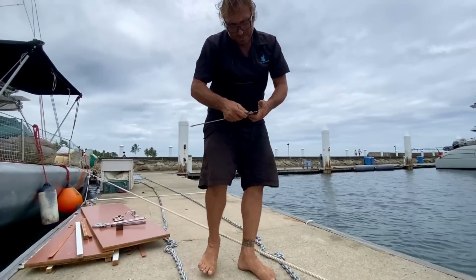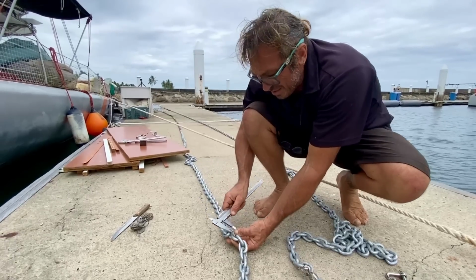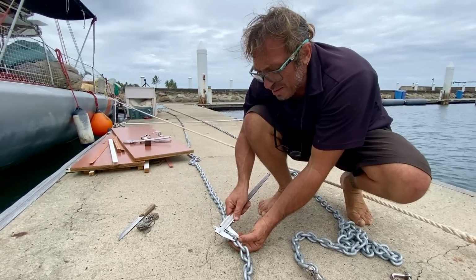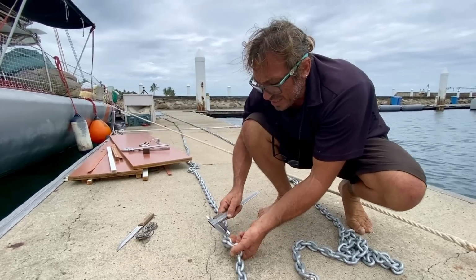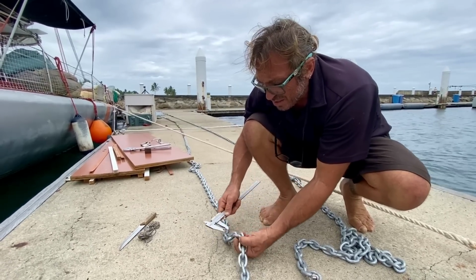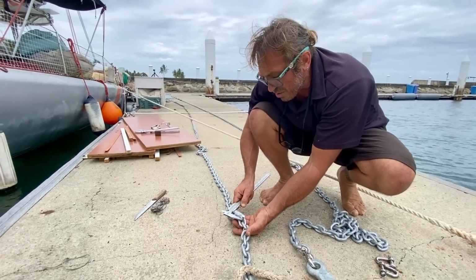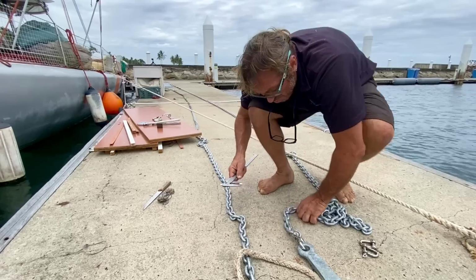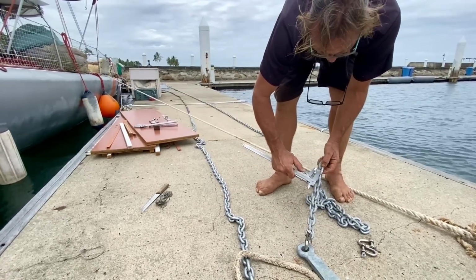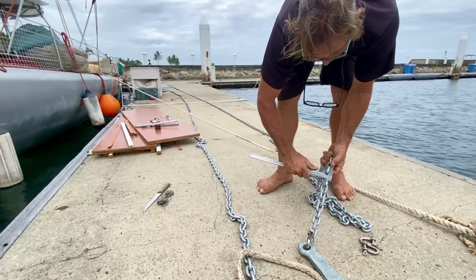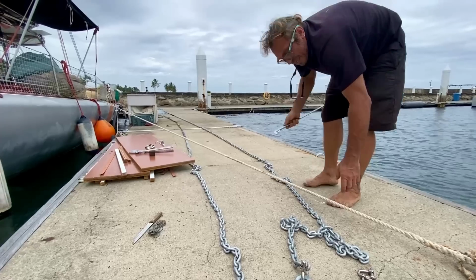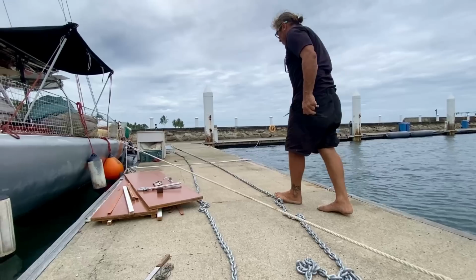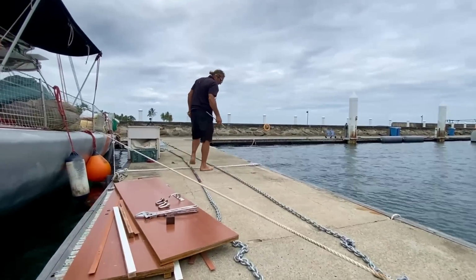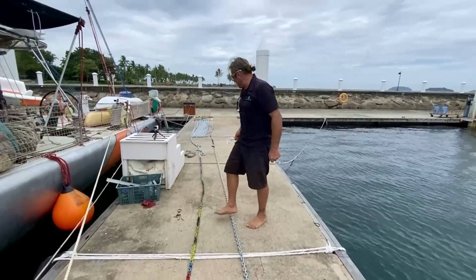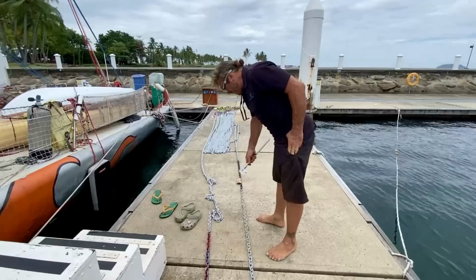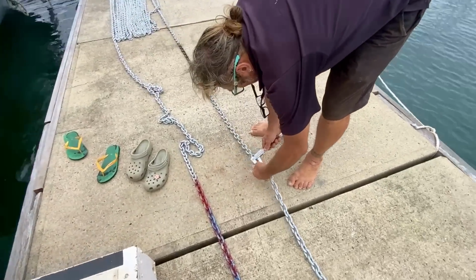The thing I want to show you is we still have one 10mm chain. Yes, there's a weld. Don't measure where the weld is, it is bigger, you see. Even if I have a little bit of oxidation, the job we do is to continue greasing and oiling. This gives us the guarantee that after 10 years we still have the same chain, because we can evaluate this 10-year-old chain. It is still a 10mm chain.